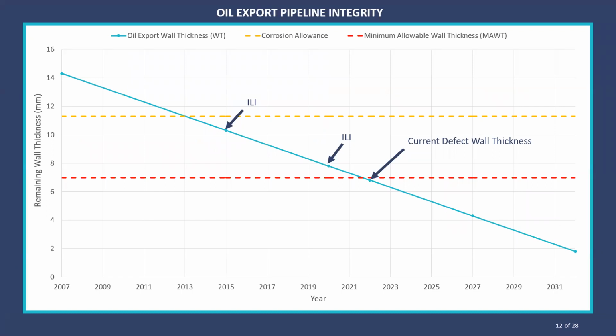Okay, so the issue I'm going to talk to you about is the oil export pipeline. We've assessed this as one of the main risks for the field today. So we've had a few historical inline inspections, which we plotted here and used to predict the wall thickness through life. And we've also calculated the minimum allowable wall thickness based on DNV standards. So that's a conservative approach, because what we know about these defects is that they're localized in the bottom of the pipeline in the first 2 kilometers, and there's 9 of them altogether.